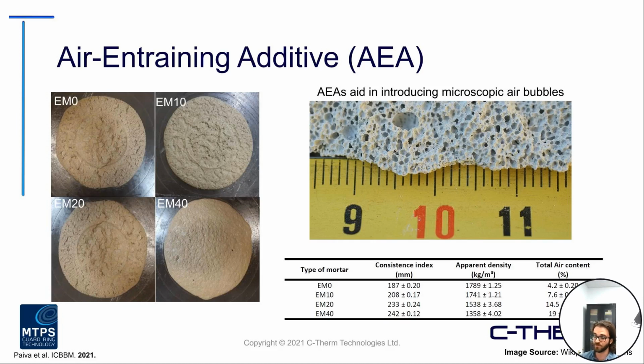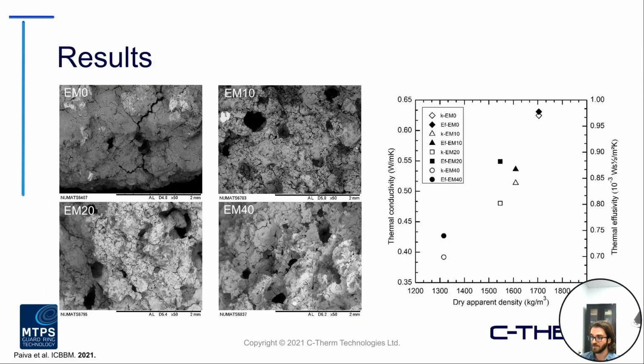So in this study, they had 4 different earth mortars with varying concentrations of that AEA additive. And what they're aiming to do is obviously thermal characterizations and also some structural and mechanical testing as well. From a density perspective, which you can correlate to the air content, as would be expected, increasing that AEA additive decreased the effective density of that material while increasing the total air content. So for the dried product, you can see some SEM imaging there, denoting that you were getting these micropores present inside the sample bulk, increasingly more with increasing AEA content. They did note there was significant cracking, as you can see in all of these SEM images. So cracking is something that needs to be taken into account.